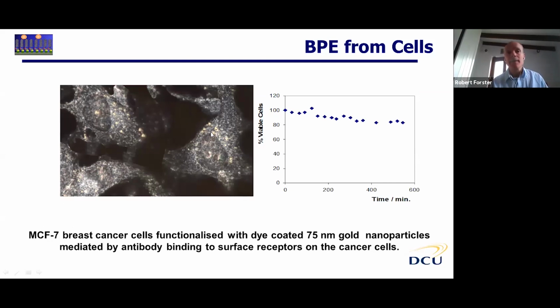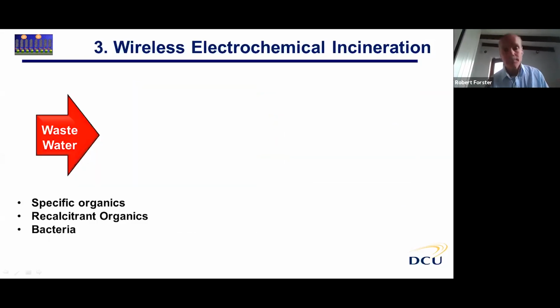These are aggregates of nanoparticles coming together, whereby the 10 volts per centimeter that doesn't do the cells any damage, you can see that over here, is actually sufficient to induce a 1 volt oxidizing potential that allows the ruthenium to become reduced to the electronically excited state and emit light.